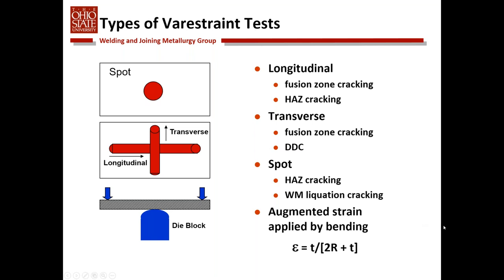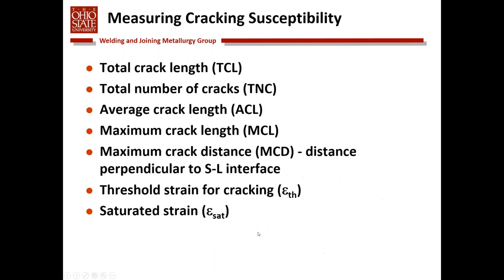The test is actually quite simple. The strain that is developed in the outer fibers of the sample as you bend it is simply determined by the thickness of the sample over 2 times the radius of the die block plus the thickness of the sample itself.